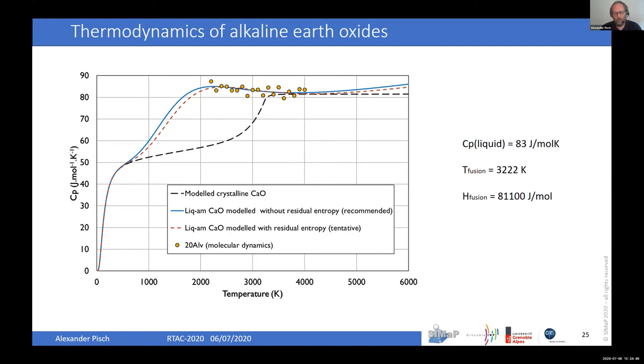This, by the way, was more or less confirmed also for magnesium oxide in a recent paper by a Vienna group, which also found a higher value in the CP. And then the fusion also was measured recently at around 3,200 Kelvin. And again, by calculation, we confirmed this value. Our calculated value is at 3,170, so very close to the value they measured.